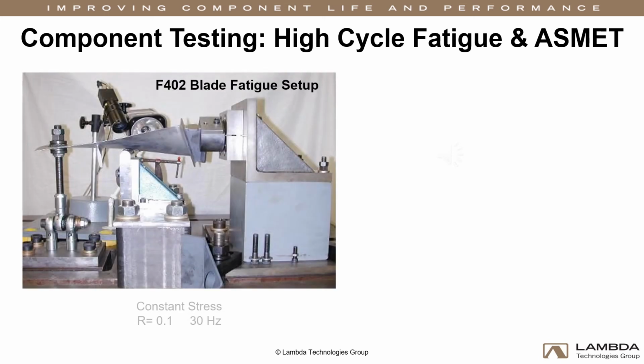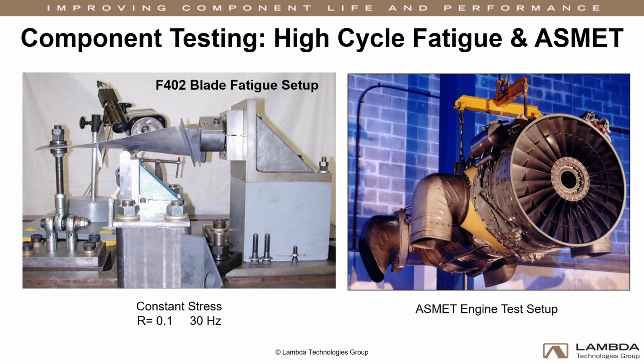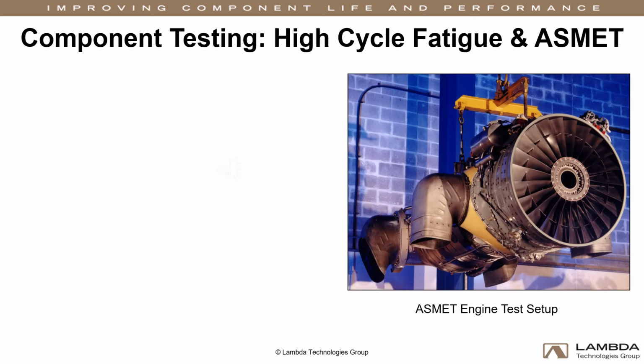Component-level fatigue testing verified that LPB treatment completely mitigates 0.020-inch, or 0.5 millimeter, deep FOD and restores fatigue properties of both test coupons and actual LPC1 vanes removed from service. Following laboratory component testing, LPB was applied to vanes for engine testing.